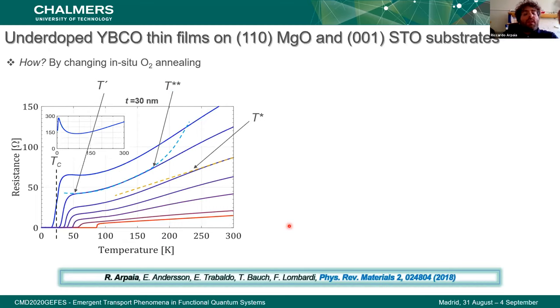So we start with the underdoped films that have been grown both on MgO and on STO substrates. And how we did it was just by changing the in situ oxygen post annealing pressure in the chamber, so after the deposition. And as you see here, we measure the R versus T of different films, just as a function of the post annealing pressure. And basically, we achieved critical temperatures going from the insulating to the strongly underdoped up to the slightly overdoped films. And of course, the R versus T curves are very much different among each other. There is a linear dependence at very high temperature, and then a quadratic dependence of the resistance over temperature at lower temperature.